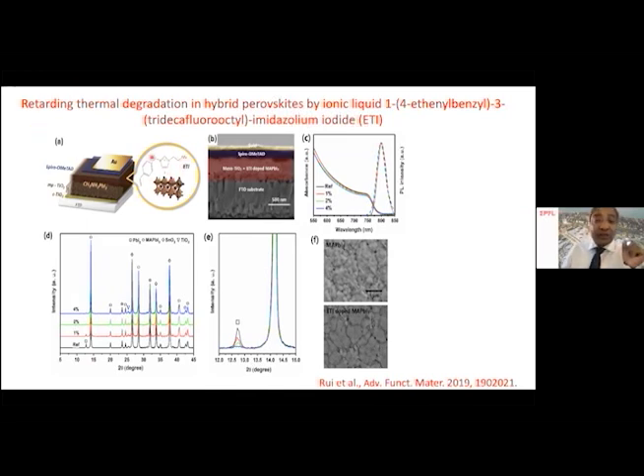And if you look at this ionic liquid, it's functionalized. On the one side, we have a double bond. On the other side, we have a fluorinated cation. You can imagine the purpose of the fluorinated cation is to create hydrophobicity of this perovskite composition. Why should we create hydrophobicity? Perovskite composition is like a salt, like sodium chloride. It attracts humidity and undergoes a decomposition process. If we create this hydrophobicity, we can avoid this decomposition process.